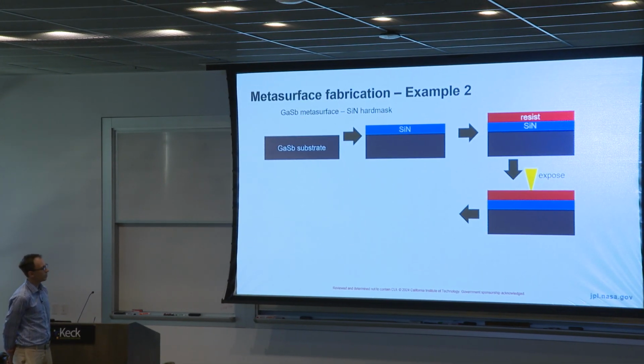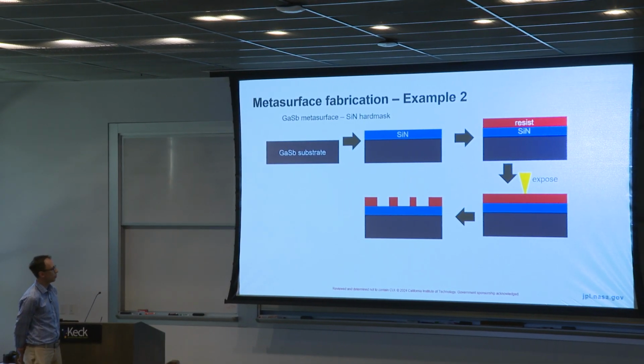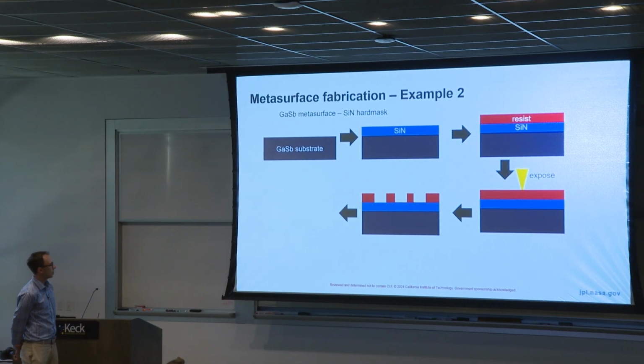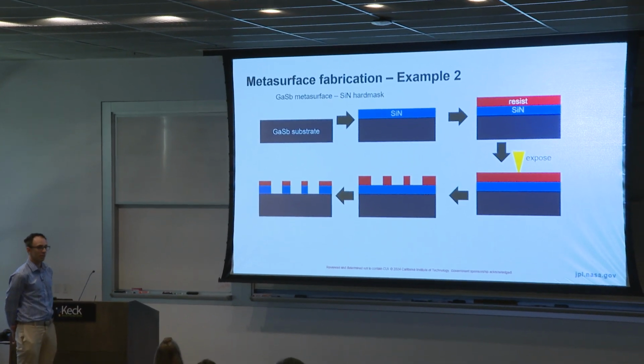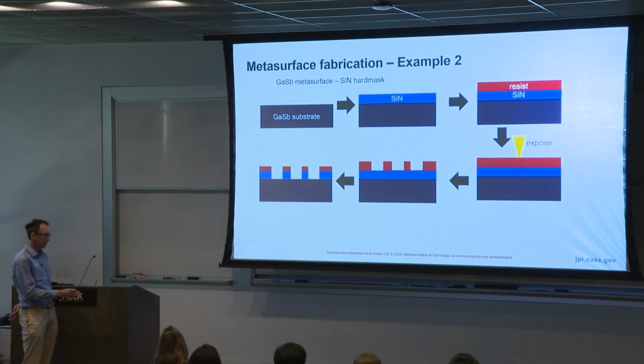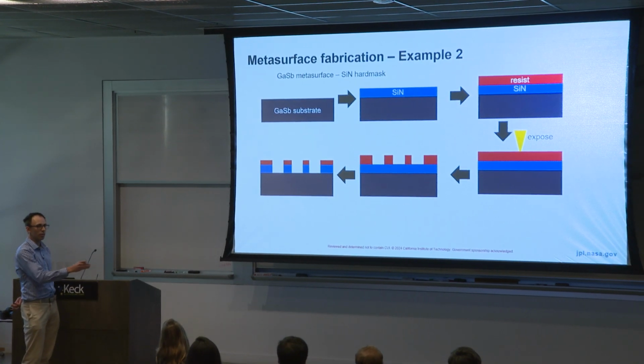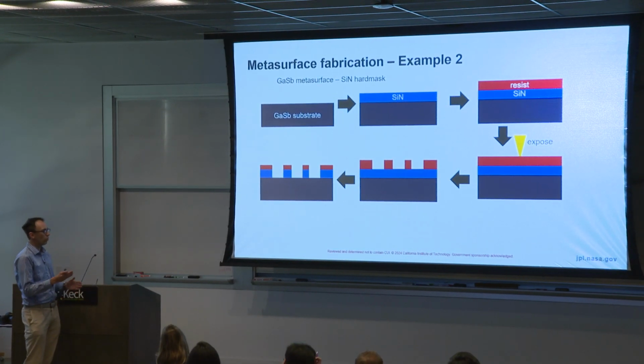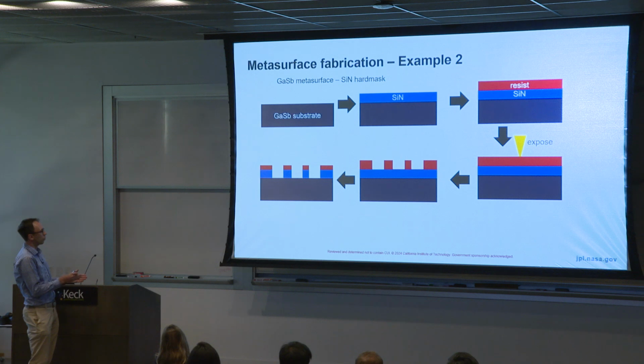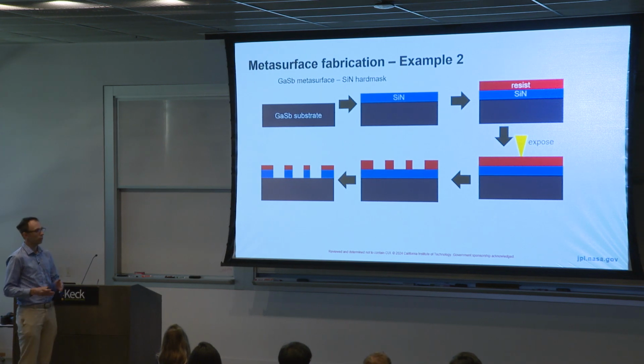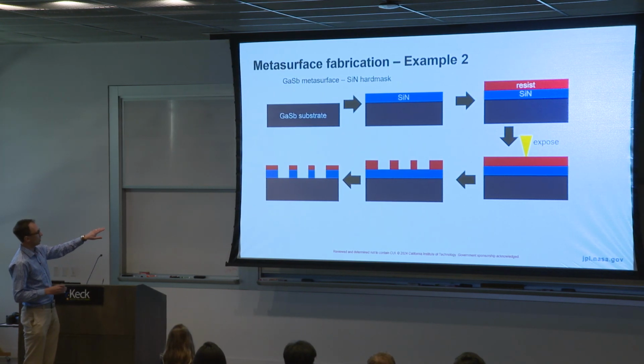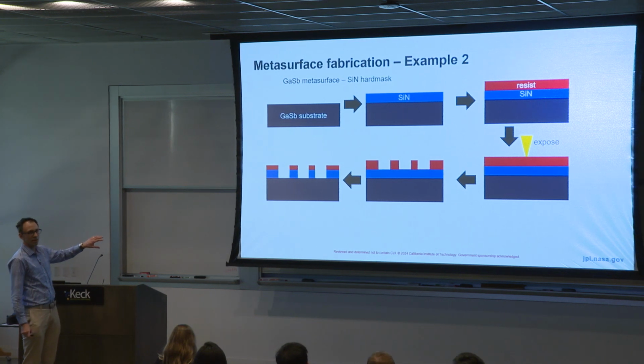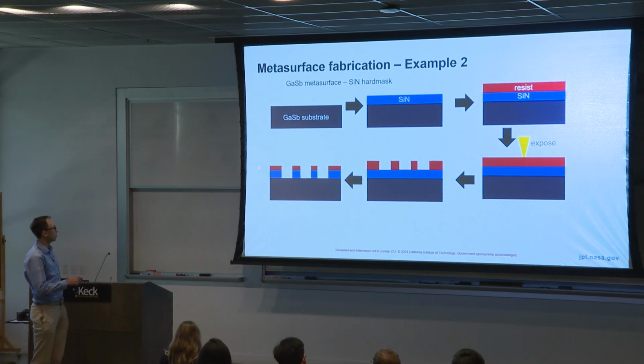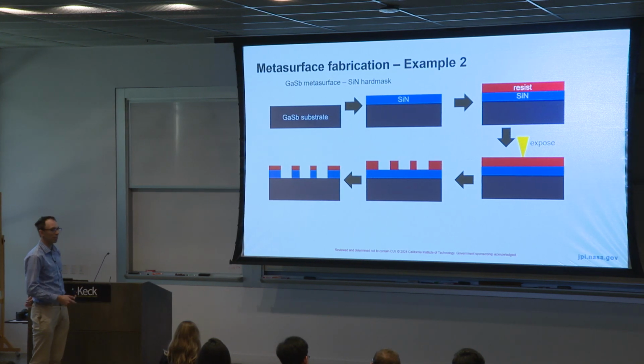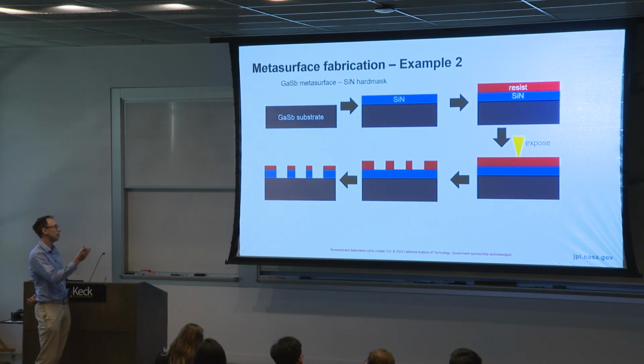You would then expose it. We know this by now, right? So you develop it. Now you have your pattern in your resist. Now you use some kind of anisotropic etch. Let me pause here for a second. Every time I say etch now, one has to consider what type of etch is appropriate for a certain material. In this specific case, silicon nitride does not etch well in the etch that was used in the previous example with the silicon. It's even using a completely different tool from the one used for the silicon etching.